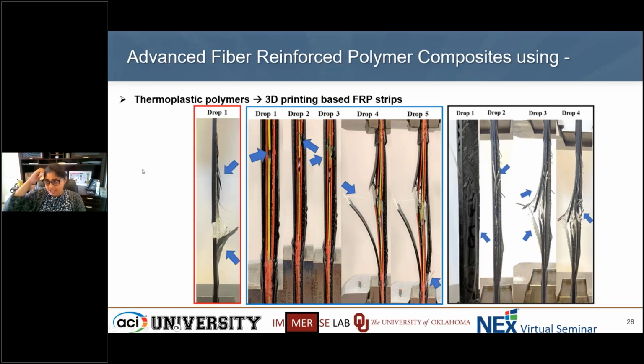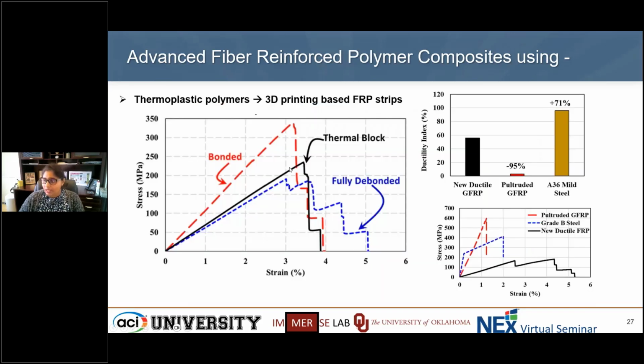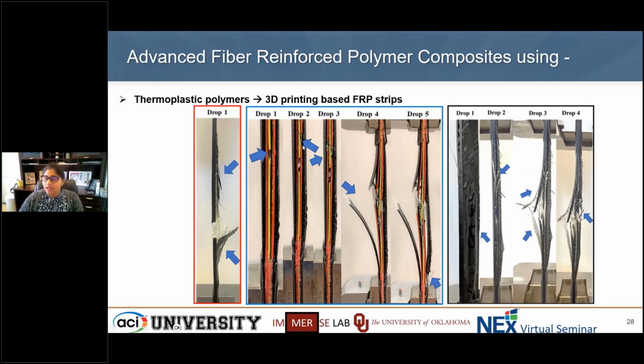Regarding failures of these composites, a simple unidirectional specimen that looks like this has also been 3D printed to make sure it's an apples to apples comparison. If you look at drops 1, 2, 3, 4, 5, this is the new ductile GFRP where one layer failure doesn't necessarily affect the other immediately. That is why we see one layer failing and still see the residual load being carried by the other layers, and then you have failure in the other layer. Then in drop 3, you have the third layer causing failure. You have drop 4 where you see the last layer subjected to failure. Drop 5, there is failure in the